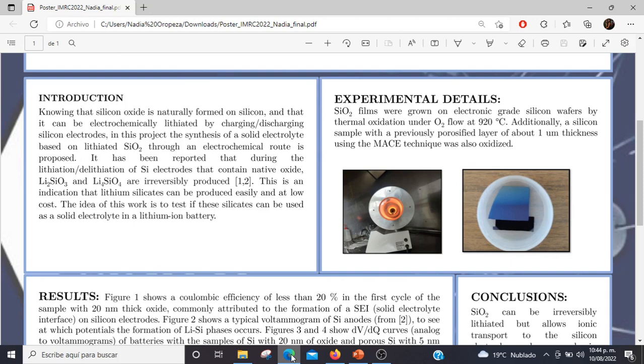First, depositing nanoparticles with a solution composed of a volume ratio of 25 to 5 of 1 molar aqueous solution of silver nitrate and hydrofluoric acid, and etching in an etching solution composed of a volume ratio of 44 to 3 to 2 of deionized water, hydrogen peroxide, and hydrofluoric acid. The formed porous layer was then transformed into oxide by thermal oxidation, with the idea that the porosity serves for mass transport of the liquid electrolyte.